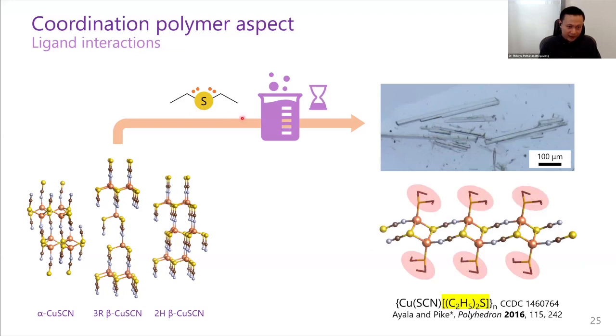So we found that actually the diethyl sulfide can coordinate very strongly with copper thiocyanate, and it produces very beautiful crystals like this. At the beginning we were excited, thinking we discovered a new structure, but actually just a couple of years earlier, a research group in the States, Robert Pike, reported the crystal structure of this material already. So it's a one-dimensional ladder type structure with copper and thiocyanate, and then we have the diethyl sulfide capped on the bottom, showing a very strong interaction with copper centers in the CuSCN structure.